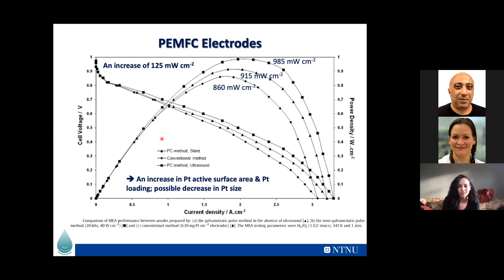So this was due to a better deposition of the platinum active on the surface, and the loading was acceptable in all places of your electrode. We also noticed that we had a decrease in platinum size, which helped.